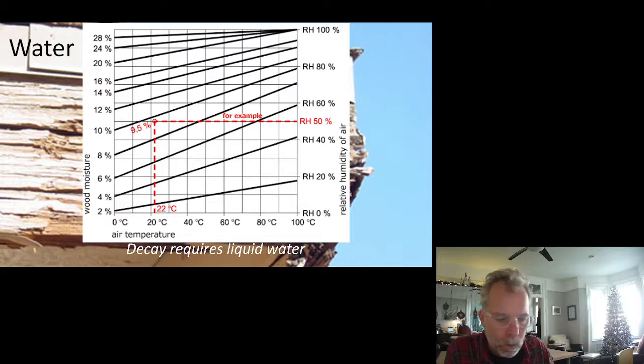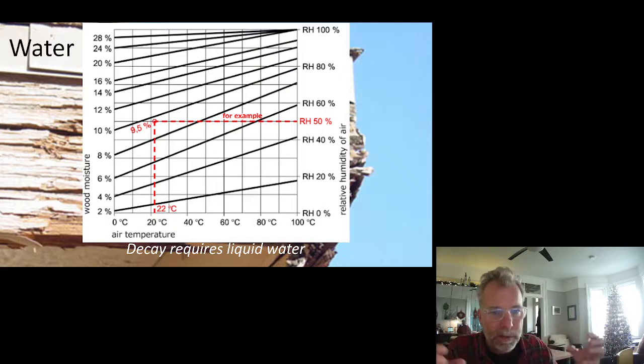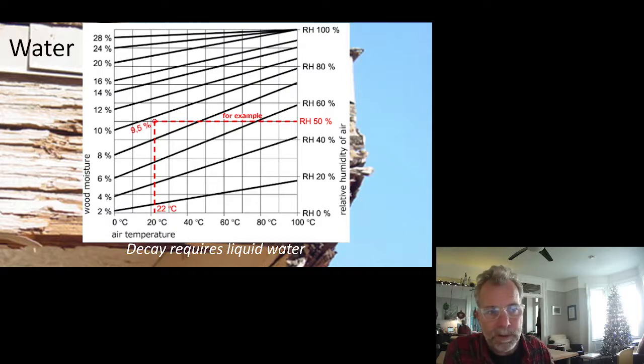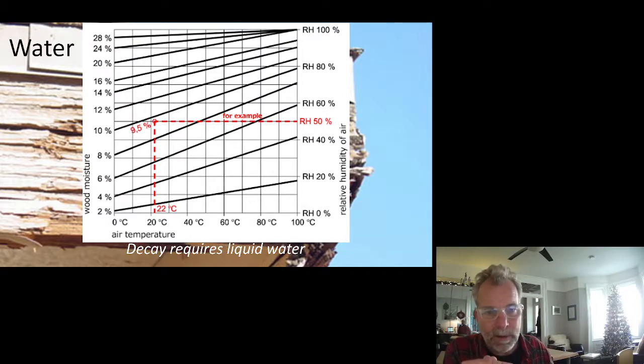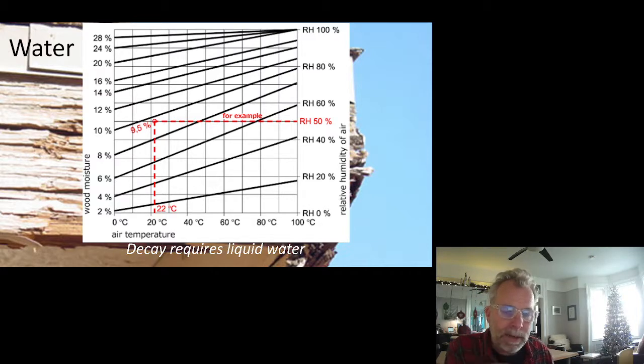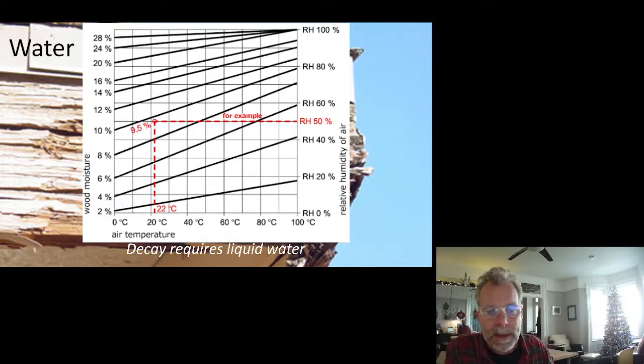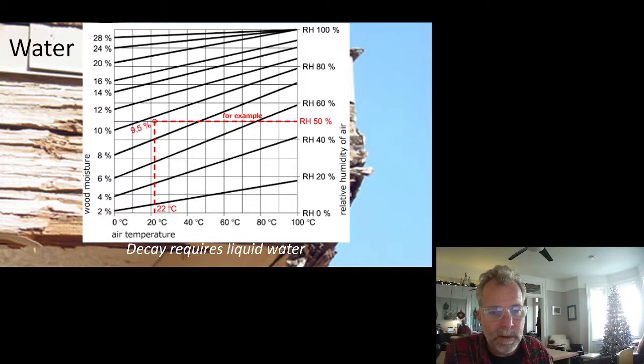Also, wood being a conductor of moisture — it has all the capillaries — and having low thermal transmission means you're less likely to get condensation in wood than in steel. With steel, as soon as you're a little bit above the dew point, you get condensation. With wood, you're less likely to get condensation, and when you do, it wicks away from the site. So wood is actually excellent in very high humidity environments like pools.